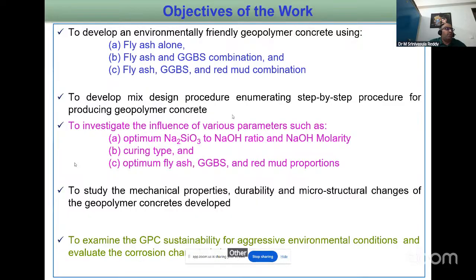What I observed with the addition of GGBS is that we can avoid heat curing. Otherwise, with fly ash alone, we need at least 70 degrees centigrade heat curing for about 24 hours. We can say the optimum is 24 hours. Beyond that, it's not adding much to the strength. So we can optimize to 24 hours at 70 degrees centigrade. If we go with fly ash alone, it takes so much time to activate and so much time to harden. So a better option is to go for heat curing, or we call it oven curing if you are doing it on a smaller scale.